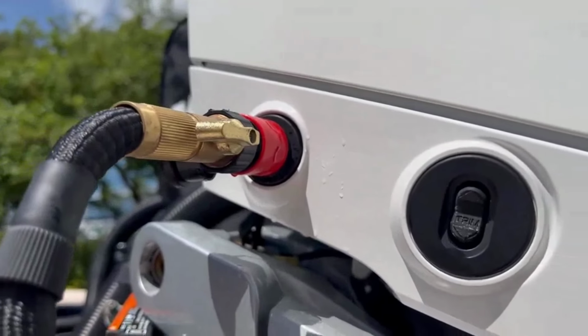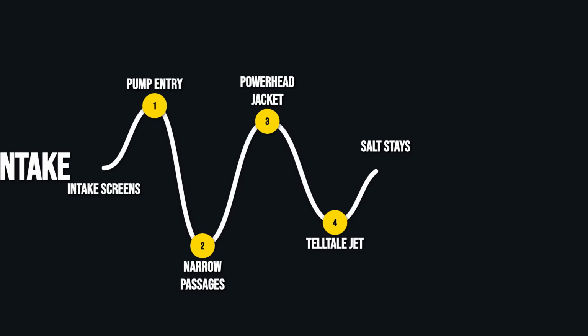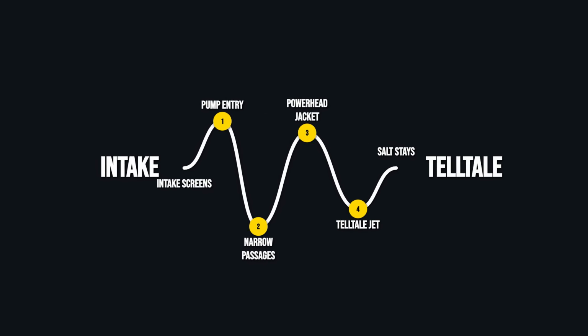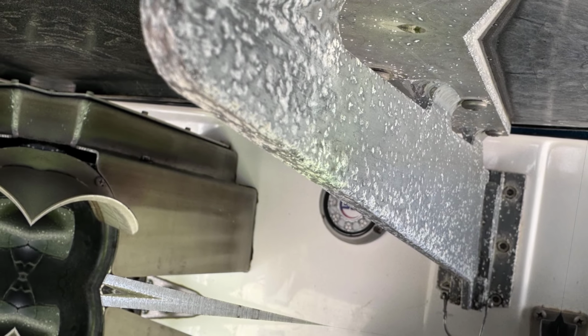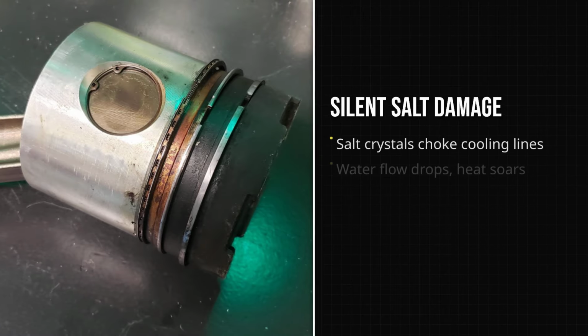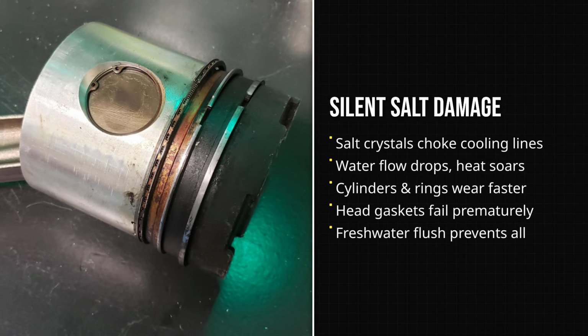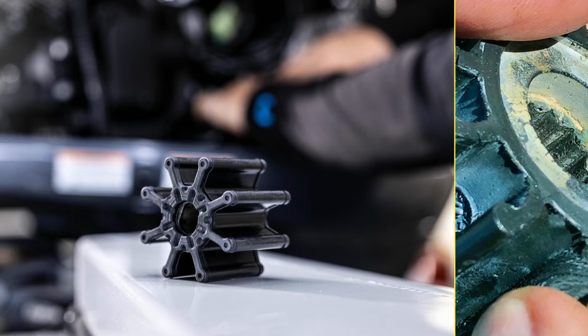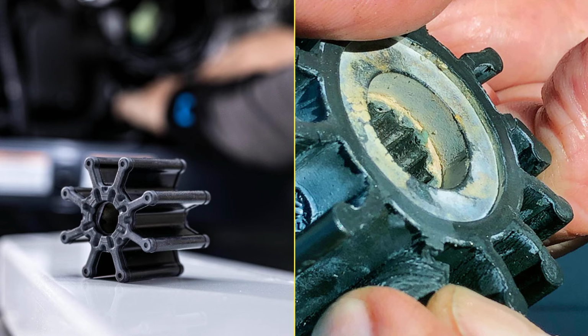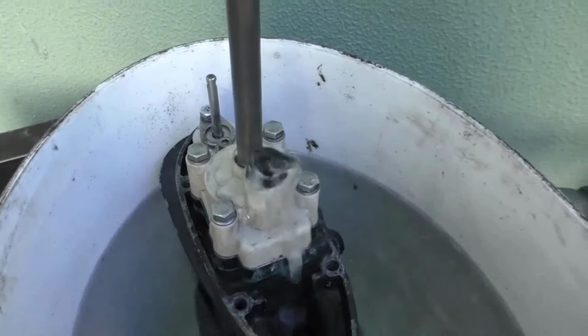Your outboard pulls raw water through intake screens, pushes it through narrow passages around the powerhead, and expels it through the telltale stream. Sounds simple, right? Except when you shut down without flushing, all that salt water sits inside those passages and evaporates, leaving behind salt crystals that build up layer after layer. These deposits restrict water flow, which causes your engine to run hotter than designed, accelerating wear on cylinder walls, piston rings, and head gaskets. And here's the kicker: restricted cooling also destroys your water pump impeller faster because it is working harder against reduced flow.